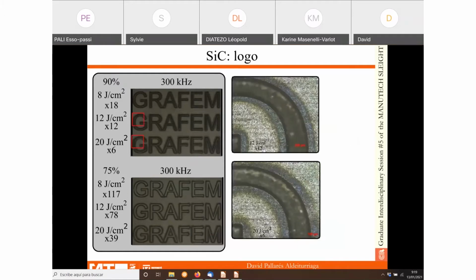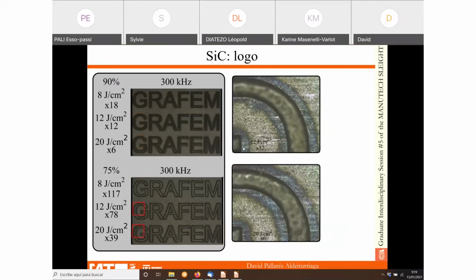Okay, if we take a closer look, then we see that the edges are okay. We don't see anything there, no micro crack, no other particular issue. If we now take a look at the 75, we clearly see the color change. Also, there is not the, how to say, the step problem, the low overlap problem that we have seen in the sapphire. Maybe it's because here we are writing several times.